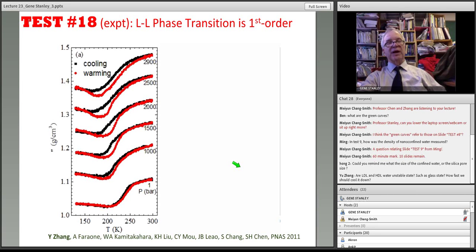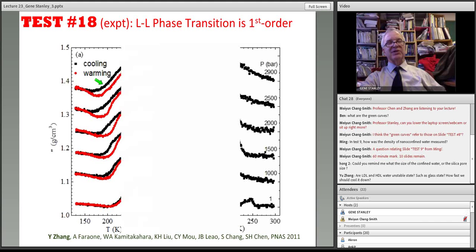And you remember we hypothesized the other data were consistent with a critical point around 1,000 atmospheres. So this is just right at the critical point. This is a little below, and even more below. And you see the two curves are cooling and warming. That means if we cool down in temperature, moving to the left, we have this black curve, and if we warm it up, we have this red curve. And this difference is the hysteresis that's characteristic of first-order transitions.